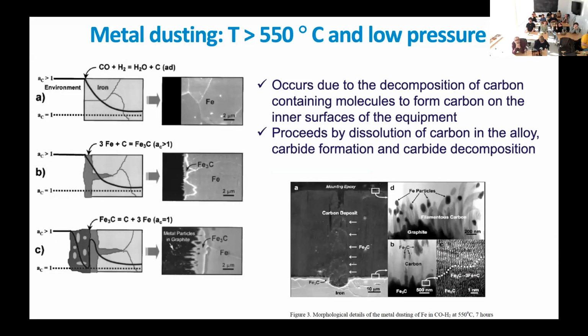And you see that the reaction is happening on the surface. Then there is the formation of the so-called cementite, okay? And the growth of cementite. Also, what you can see here is that there are some iron nanoparticles on top of filamentous carbon that participate in further catalytic reactions on the surface. So you see what kind of damage can happen in this case.